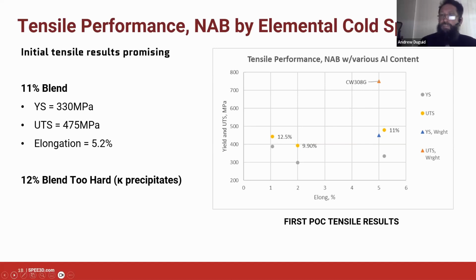The 12.5%, by contrast, we would have liked to think it would have sintered even better, but it's really bad. Why is that? Well, we think it's probably because we've got too much coarse kappa precipitate in it, and that's obviously causing the fracture toughness to collapse, and therefore we're getting a brittle failure rather than a ductile failure. So anyway, that's a good place to land in terms of a proof of concept. We're pretty happy with that. So we might go on to the next slide.